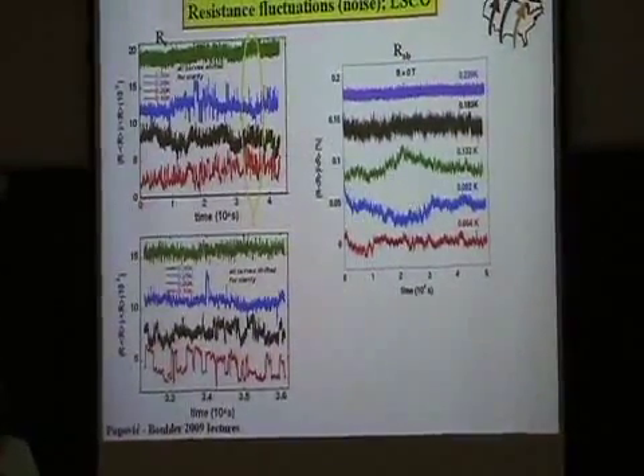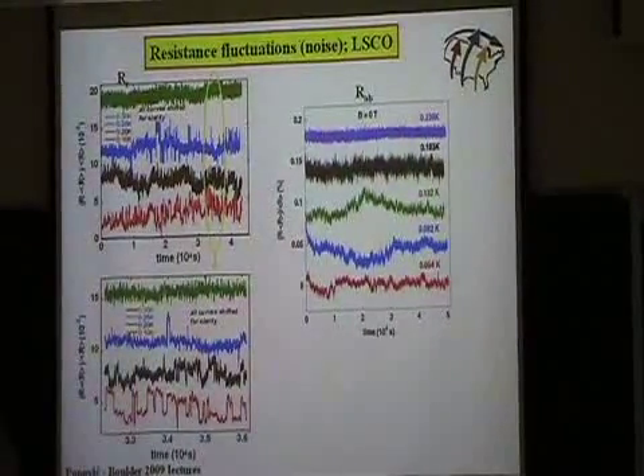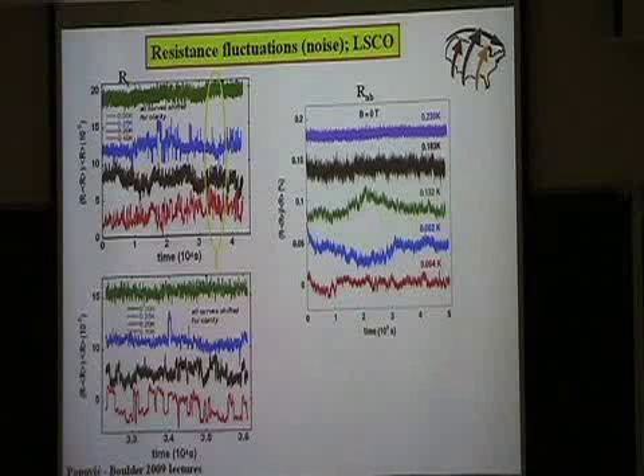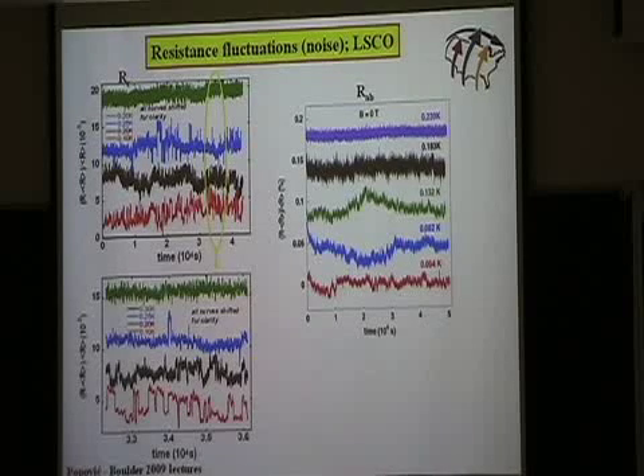Well, I don't want to say don't take it too seriously, but sometimes you see these switching effects, but you don't see them always. In fact, most of the time you don't. This could be because we have these magnetic domains and these spins maybe flipping also. Spins or domains, actually? Well, the spins, but then they should affect the domain walls also. These are anti-phase boundaries, so everything should change. I'm not sure, maybe it's because of that, I can only guess. But yes, here we did see some switching, but most of the time you don't see it.